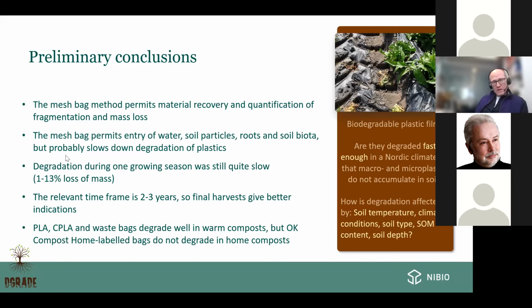The degradation that we did observe, however, was very low, not more than 1 to 13% during a growth season. And we're not expecting much to happen during the winter season where temperatures are substantially lower. But we're now treating the 52 weeks, and we will harvest this year the 104-week treatment. The relevant time frame here is, of course, 2 to 3 years. So these final harvests will give us better answers to our questions.